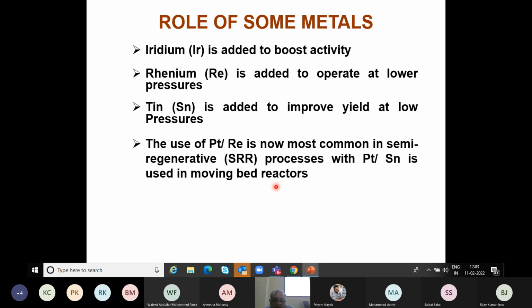When the two metals are equal, this is called a balanced catalyst. It is called balanced catalyst because each of these metals is equal: 0.3% platinum, 0.3% rhenium, or 0.3% platinum and 0.3% tin. But over a period of time, people also discovered that if you put more of the second metal, for example 0.6% rhenium or 0.6% tin, then the coke deposit reduces significantly. So this is called skewed catalyst, SKEWED. It is called skewed catalyst where the rhenium content is higher than the platinum. So this is also unbalanced, but it actually helps you.